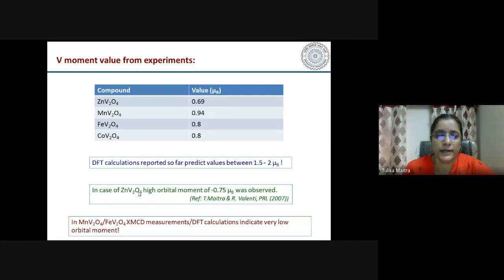Okay. In case of zinc vanadate, we had shown earlier that this compound has a high spin orbit coupling, which gives rise to a very high negative orbital moment, which then cancels out part of the spin moment, giving rise to a low magnetic moment. Okay. But for these MnV2O4 and FeV2O4, the experiments and the DFT calculations indicate that this spin orbit interaction is not very high in these compounds. So there is no high orbital moment or cancellation of the spin moment by orbital moment. So what is then causing the lower moments in these 3 compounds?